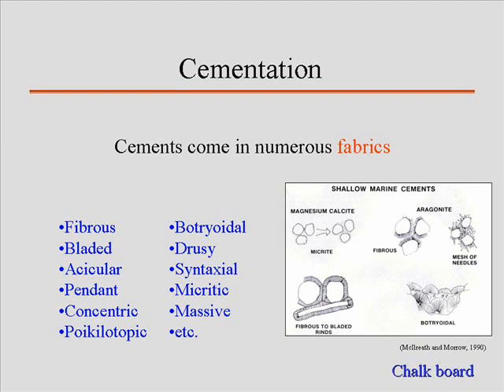Consider the following. Suppose now you've got a sandstone which has a first phase opal cement. Now, opal is not the opal that you're thinking about from Australia where you can buy a pendant and everyone's going to think it's cool around your neck. This is better called opal CT, which is cryptocrystalline, often biogenically produced, non-crystalline silica with a little bit of water in it. When opal forms a cement in a marine environment, the first thing it does is coat all the grains. Now remember, this is a situation where you have water completely enclosing the grains. You end up getting a very thin precipitating layer of opal. Unfortunately, opal doesn't form really good crystals, so you're not going to see really beautiful crystals of this stuff at all. It's just going to look like a thin rind of stuff around the grain.